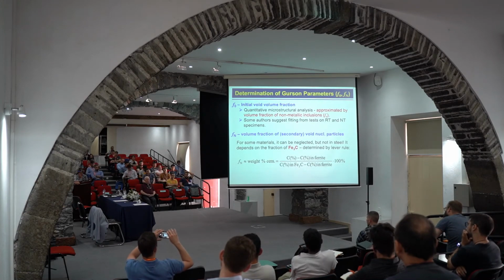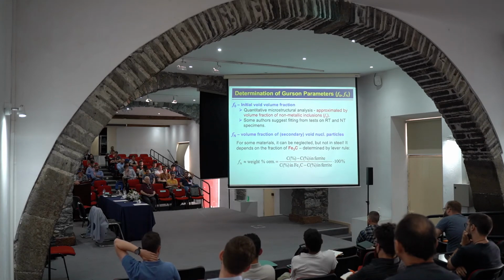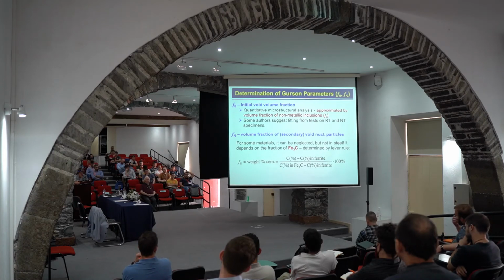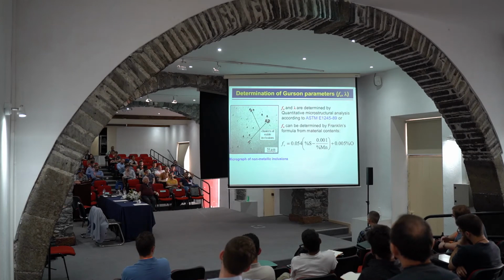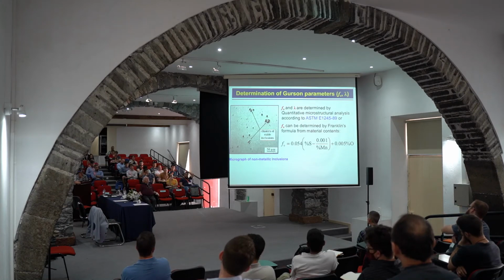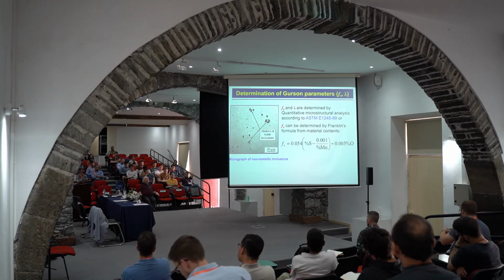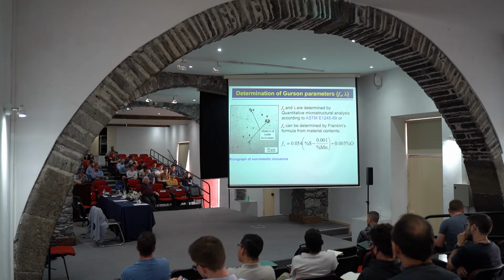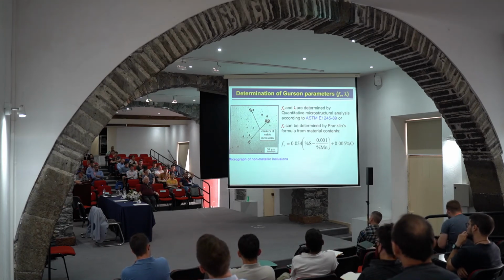So we would need the initial void volume fraction. This is a relatively simple task. It is done by microstructural analysis. And then we would need some other parameters which are also related to volume fractions, void volume fractions. You can see how this is done using microscopy. But at this point also let me emphasize another parameter which is actually not in this scope, but it turned out to be an essential one, and that is lambda. Lambda is the mean distance between inclusions.